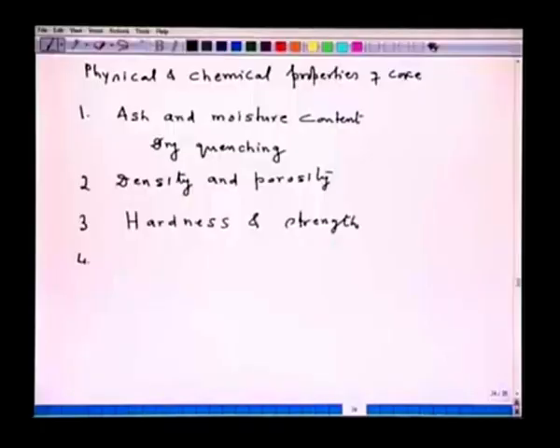Then the fourth important thing is the reactivity of coke. For reactivity, coke should be porous, so that the oxidizing component of air can diffuse and the carbon can react. But well, more porosity is good from the reactivity point of view, but from the strength point of view it is not good. So, an optimum has to be reached, because the most important part of the coke is the strength. If it breaks during its downward movement, then it will affect the permeability, and the whole smooth functioning of the blast furnace will be influenced. So, the strength is more important. Of course, reactivity is also important, but one has to compromise over here.